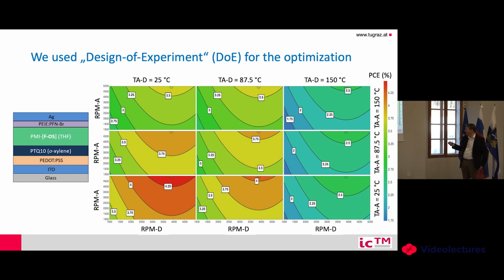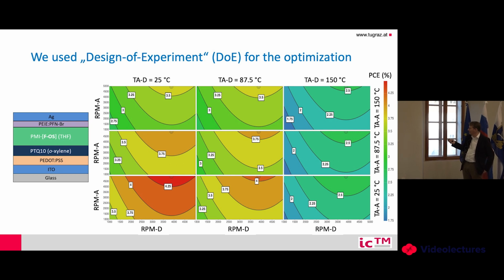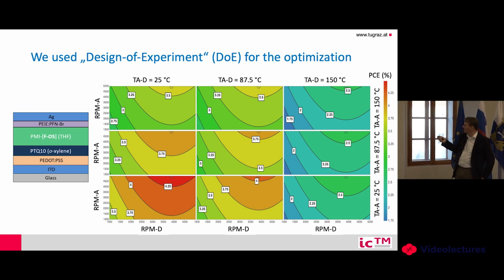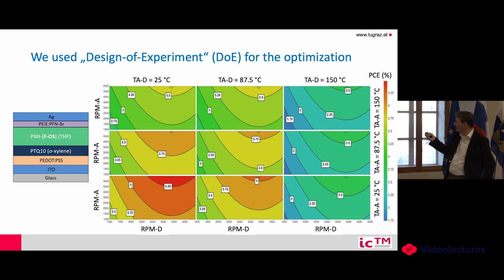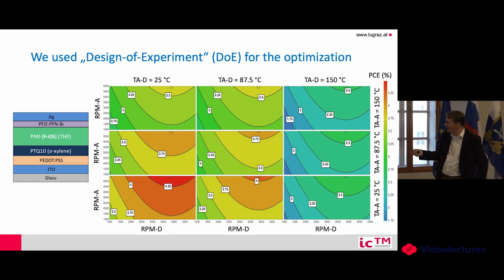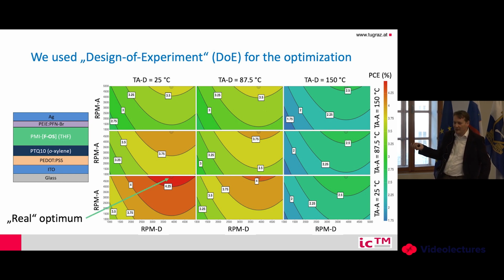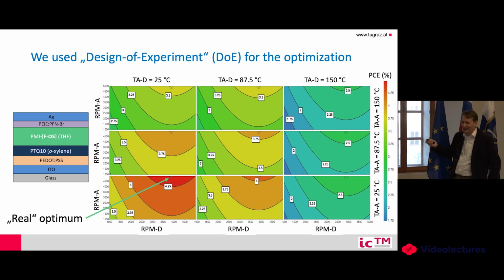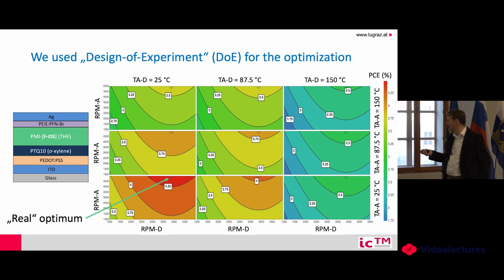So by changing different temperatures, you see, we did it at 25 degrees or room temperature, slightly above, and 150, and we changed the film thickness. We really found a sweet spot. We didn't do this experiment, this was just a prediction. If we would process under these conditions, we should find the optimum conditions. And actually, it turned out it was really the sweet spot, and we get the best efficiency under this one.